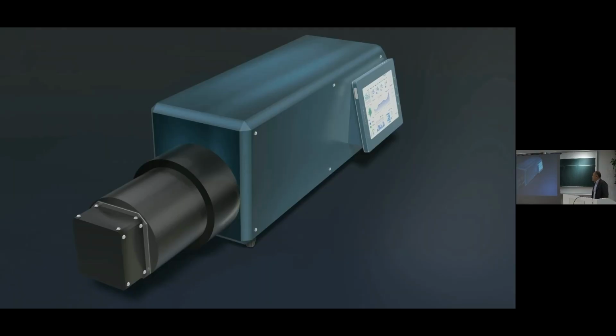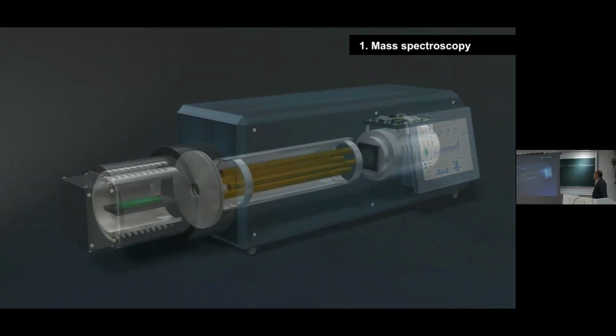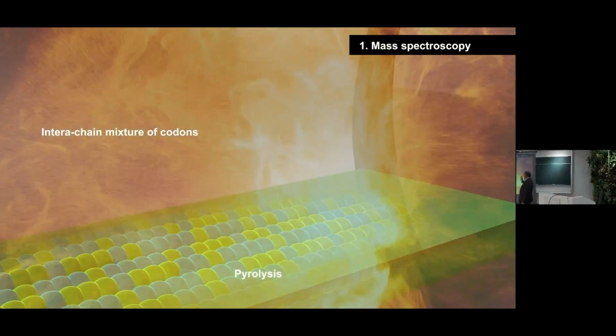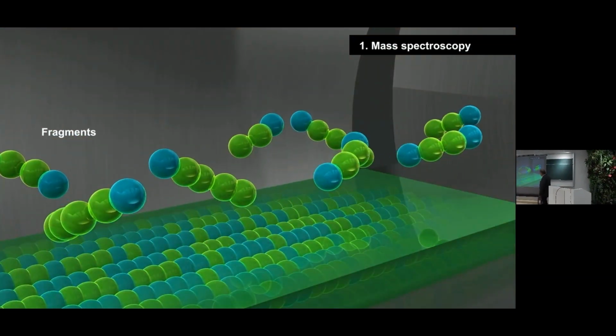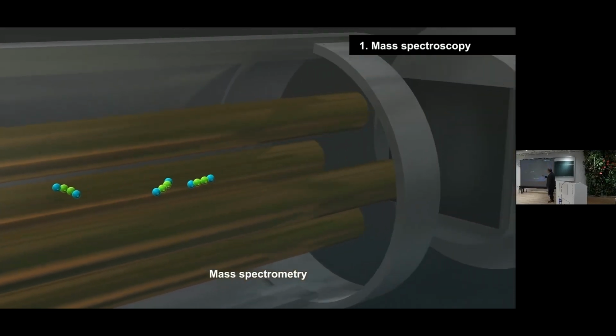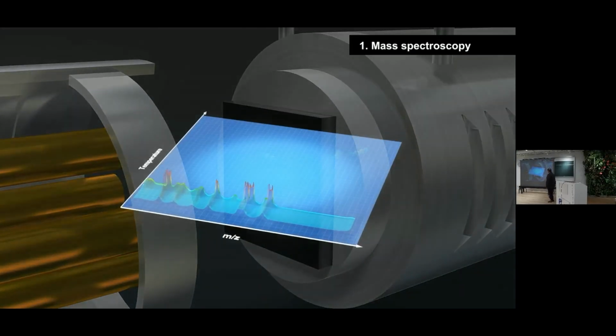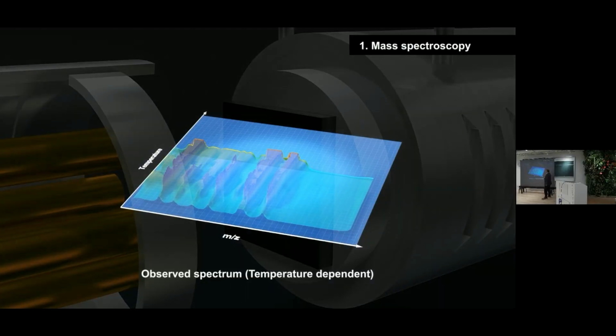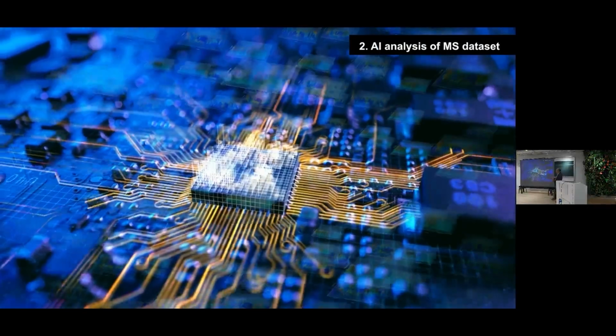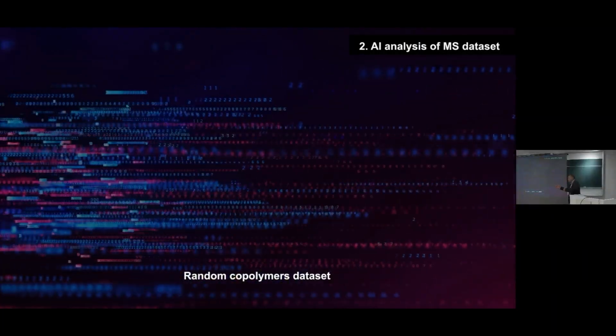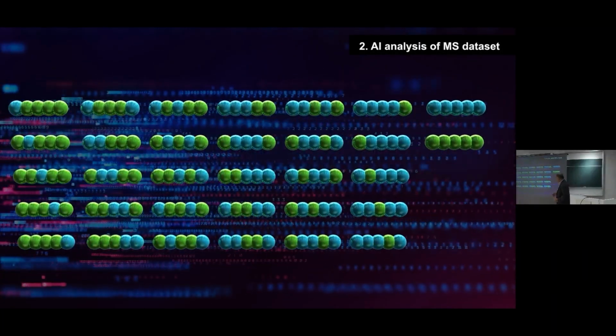Okay, so this is the cartoon of our method. First, I put the samples in and pyrolyze them from room temperature to 600 degrees Celsius, and then make the fragmentation data and monitor it as a heat map. Of course that is a kind of big data, but this is not enough for the NMF analysis. So by changing the composition ratios, we obtain similar data. That is necessary. We have to do that.